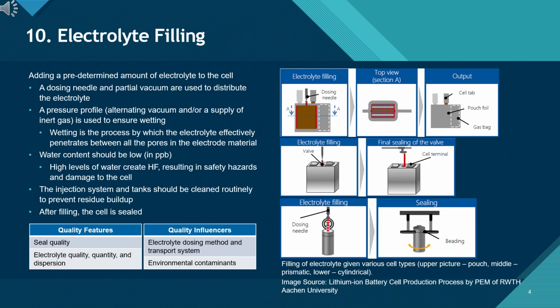Step 10 for electrolyte filling. In this step, we introduce a precisely measured volume of electrolyte into the cell. A dosing needle injects the electrolyte while a partial vacuum helps draw the liquid deep into the internal structure. The system then applies an alternating pressure profile, vacuum, and inert gas backfilling to ensure full wetting of both electrodes.